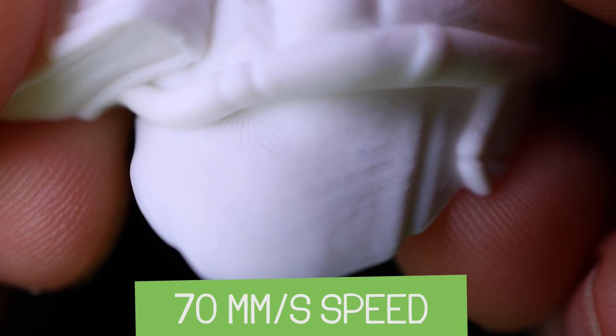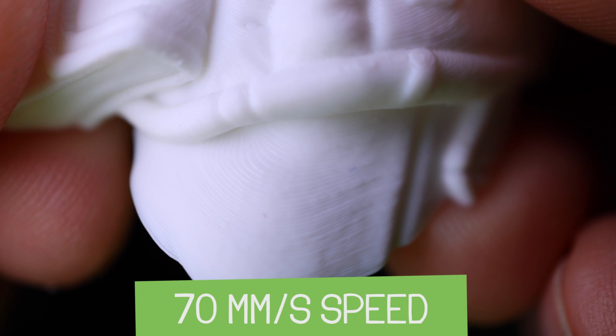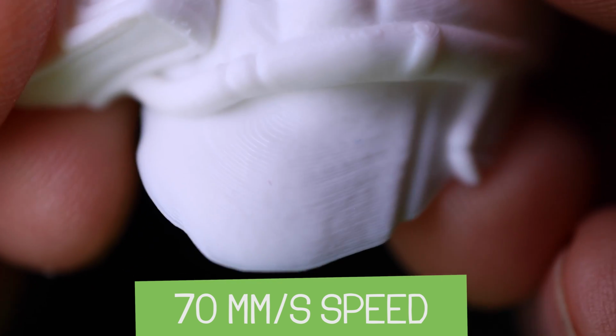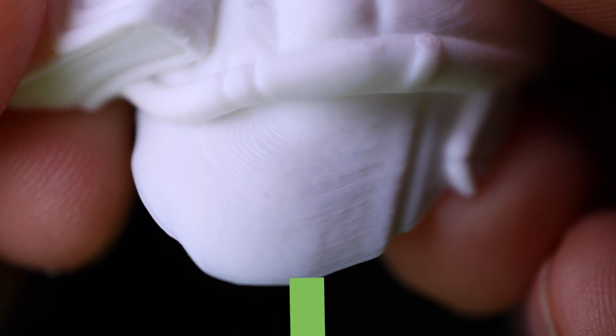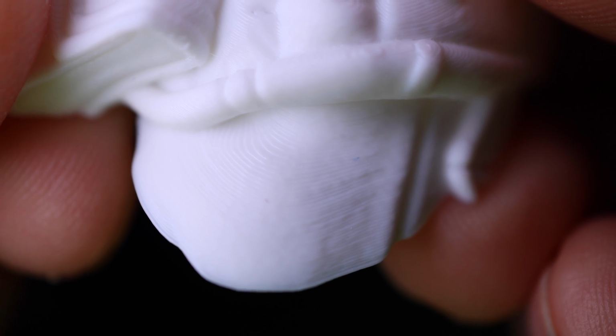So this is printed at 70 millimeters a second. And you can see how some of the edges at this magnification are a little rougher, and it's because the speed is going so fast, it can't push out the filament in a constant flow at that speed. If you look on the side of the face, you can see some imperfections, because that's where the filament either starts catching up and pushing out more than it needs. You can get over or under extrusion when you're printing too fast. You can see how some of that happened right here, and you can see some patterning that's not the layer lines, and it's just because of over extrusion, and that's where you can really start to get those zits. And if you're getting some of those issues, it could be your print speed and you need to just slow down.